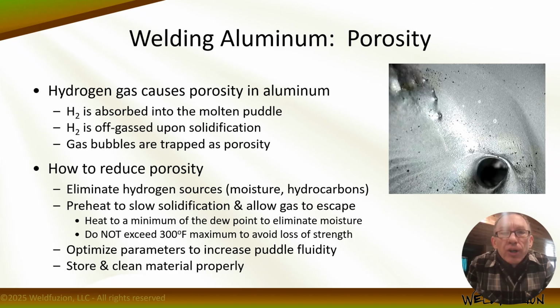All right, you can also optimize parameters for a more fluid weld puddle that solidifies slower and allows more time for that off-gassing to occur. This assumes you've got good argon gas coverage and sufficient flow rate. But I first saw this working in industry with early TIG inverters like the Dynasty machine from Miller. Customers would change from a conventional square wave machine like a Syncrowave, and all of a sudden they would start seeing porosity when making the same welds with a Dynasty. Swap the leads and consumables back to the Syncrowave, porosity would go away.